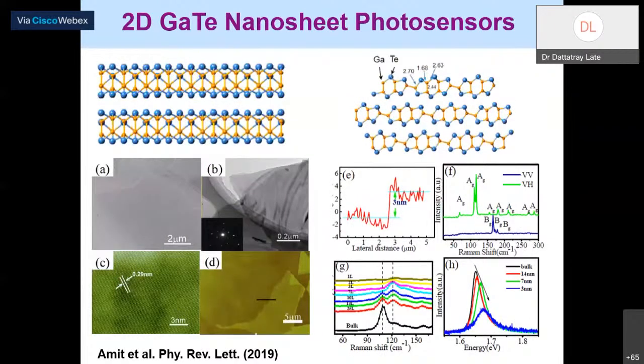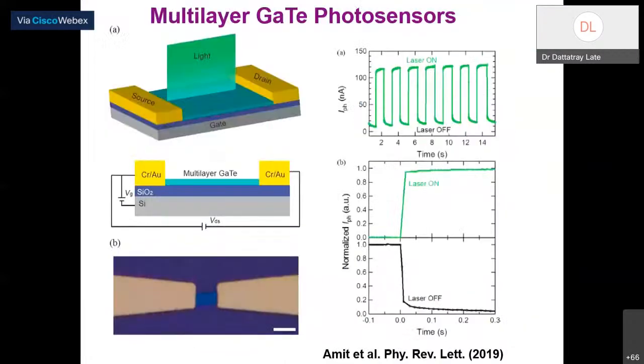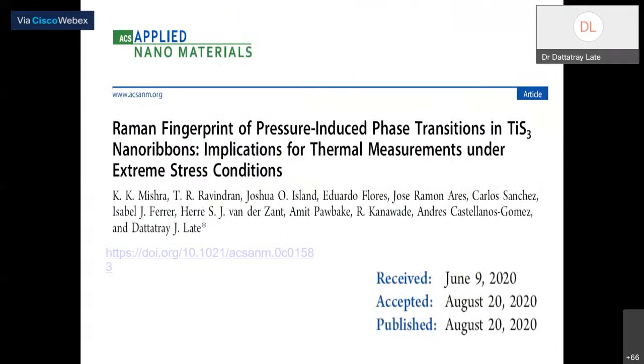And this is another material which is known as gallium telluride. Also, we find the same result for Raman spectroscopy, right? For 3 layer, 2 layer, 1 layer, the bonding between gallium and tellurium becomes so weak and we are not able to collect the spectra. Again, it has a very good application for, say, photodetector and gas sensing application.